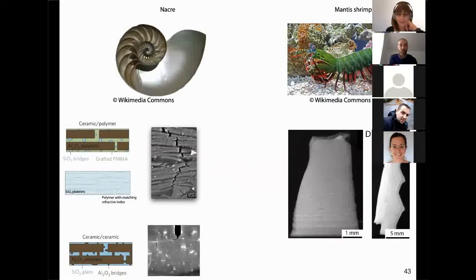So I just want to summarize a bit what I've been showing here. Starting with nacre, this is one of the toughest natural materials we know of. And the microstructure is very interesting and has very different reinforcing mechanisms. What we've seen when we try to mimic it is that when we have a weak interface, and by weak I mean a different class of material at the interface, like polymer or metals, what we end up with most of the time is bridging. So we don't see all this nice platelet sliding we would see in natural nacre. We only see some deflection and some bridging as reinforcing mechanisms.